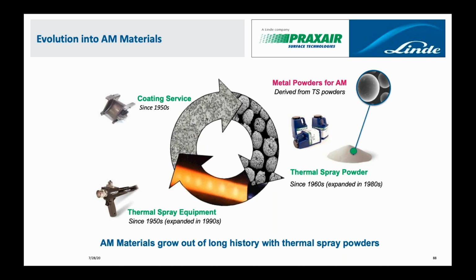And that's how we got into making these materials and powder. So Haynes made the sheet and the wrought material, and we made the powder primarily for thermal spray. But thermal spray, you could say, has a history in additive. Early on, let's say in the 80s when I started interning here, we were making copper alloys that were being spray formed in a vacuum plasma spray system for rocket engines by NASA and others. Then in the 90s, we were working on cold spray. We were accelerating powder even faster, using a helium gas. Cold spray is now considered an additive process. And we'll go on. So next slide.